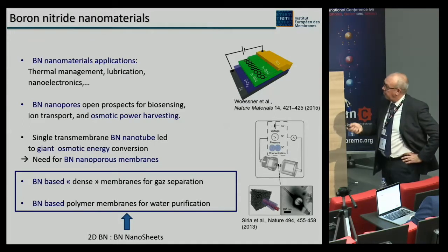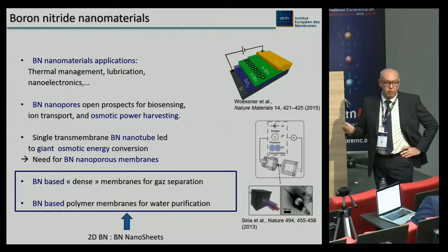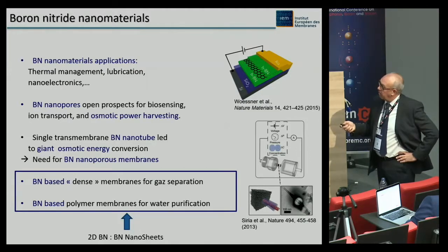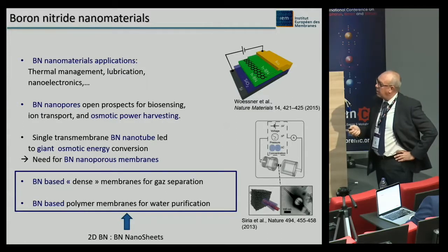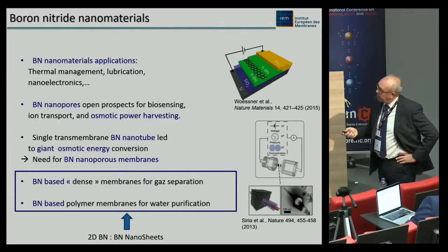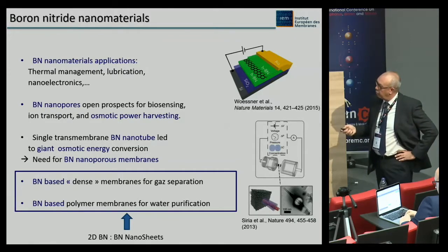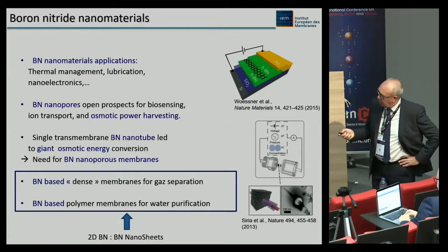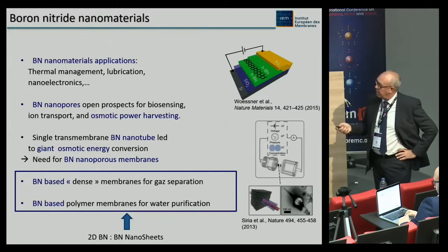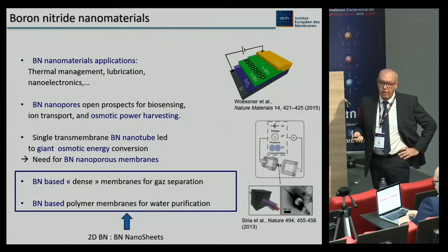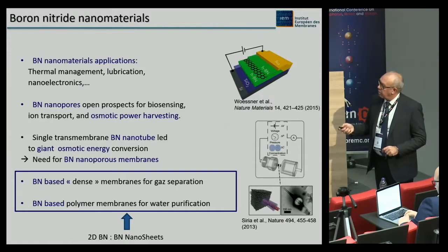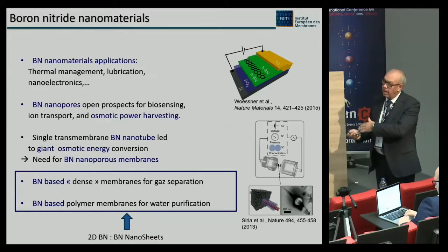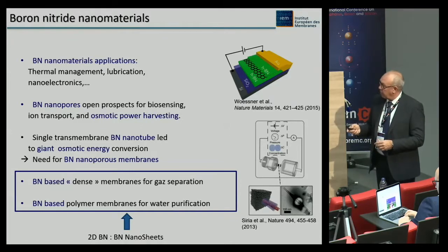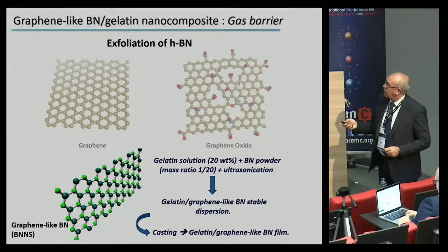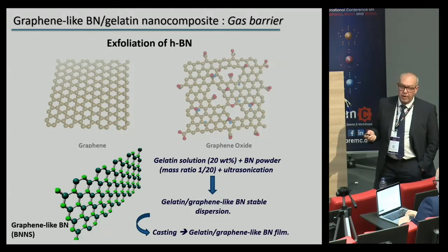These very nice papers show the potential of these materials for the osmotic power harvesting, and also as BN nanoporous membranes. I will just show you today two examples of what we've done in the group based on BN: dense membranes for gas separation, and also a very new study for polymer membranes for water purification. The idea is to use 2D boron nitride particles inserted in this system to prepare new materials. This is very simple, contrary to the previous part, in which the chemistry was much more difficult to perform. So the first idea is to prepare these boron nitride nanosheets.